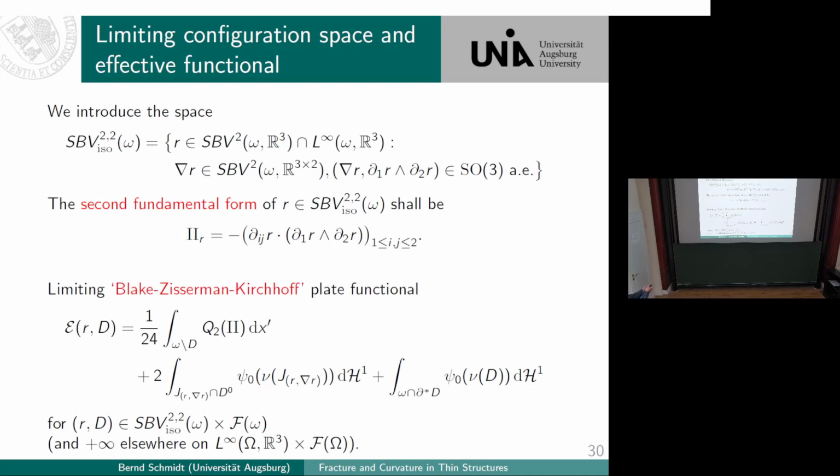If you look at the first line here, and neglect this D here, it's exactly what you know from Kirchhoff's theory. It's exactly the Q2 here over the second fundamental form, right? But then you have additional contributions. So again, there is this additional contribution for voids that survive. And there's another crack contribution for voids that collapse into a single crack. And again, why don't we just call it a Griffith term here?